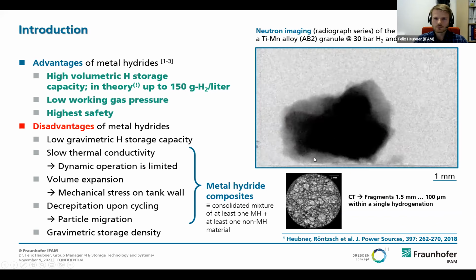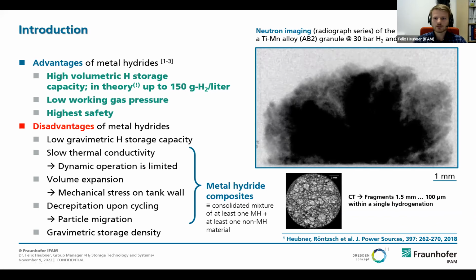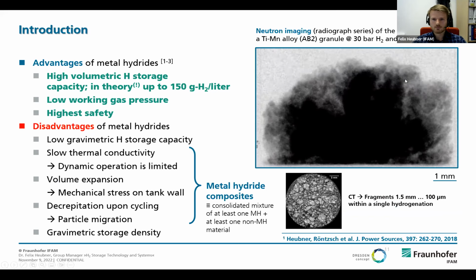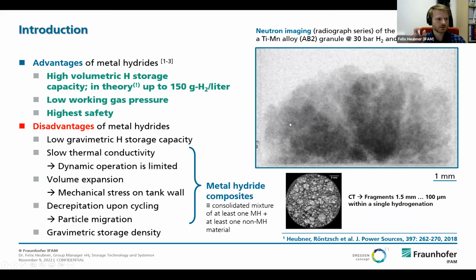I want to show you this radiograph sequence of a granule of 1 centimeter diameter absorbing hydrogen. So now it has already absorbed hydrogen in a few seconds. And from this granule results a powder bed after only 1 cycle, because this was a very brittle material. It was titanium manganese based. And after 1 cycle, we had fragments between 100 micrometers and 1.5 millimeters. So this needs to be taken into account when designing a storage system based on hydrides. All these points: low thermal conductivity, volume expansion, decrepitation upon cycling, these particles becoming finer and finer during cycling, are topics elaborated in R&D projects in the last years.